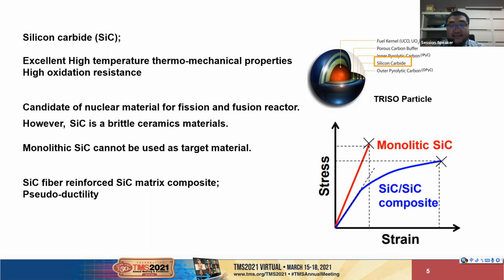But the good thing is that people came up with an idea to fabricate silicon carbide composite by reinforcing the monolithic silicon carbide with silicon carbide fibers. As you can see, in this stress curve, the monolithic silicon carbide is very fragile and easy to break, but the silicon carbide composite becomes much more ductile.